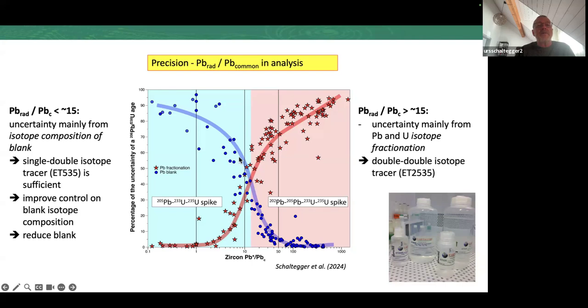When we have radiogenic to common ratios which are smaller than 15, the uncertainty is dominated by the uncertainty on the isotopic composition of our blank, so our common lead. We think that there is no common lead in zircon mostly. The lead has no space in the zircon lattice. But what we find as common lead in our analysis is actually what we have added through the procedural blank. And when this is the case, at these lower radiogenic to common ratios, it's sufficient to use a single lead, 205 lead, double uranium isotope tracer. And we can only improve the situation by having better control on our blank isotope composition, that is, smaller uncertainties on the composition we use, or we can reduce the blank, to get to higher radiogenic to common ratios.